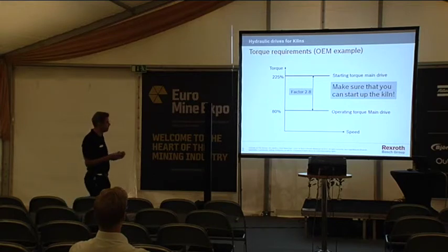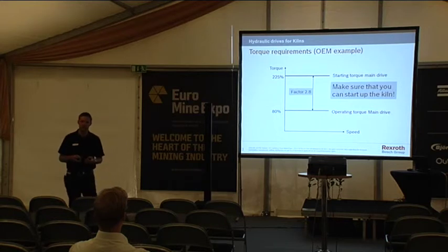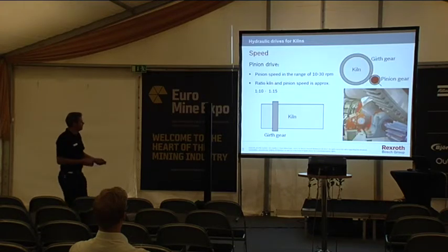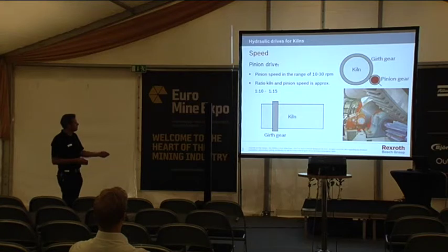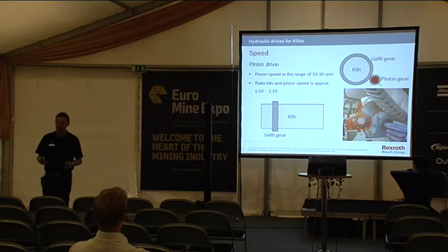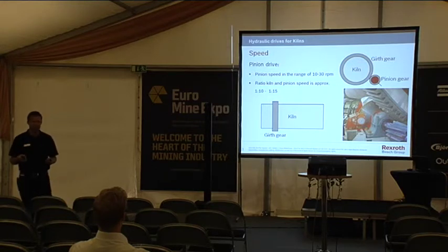So then you realize it's difficult to find a good and efficient drive system that can be optimized for all drive cases. And normally you have a pinion and a girth gear solution. The girth gear is around the kiln, and then you have the pinion attached. This is the pinion and this is the girth gear. The drive system is attached to the pinion. And if you have problems with synchronization or balancing of these drives, you will get a lot of wear on the girth gear and on the pinion. And the lead time for this girth gear and pinion is very long, and it costs a lot of money. So that's an unwanted situation.